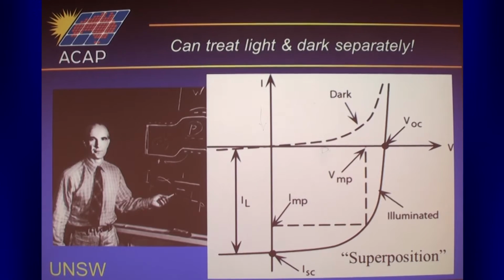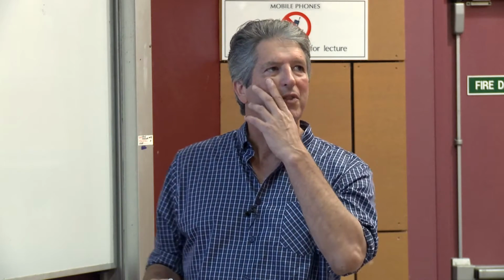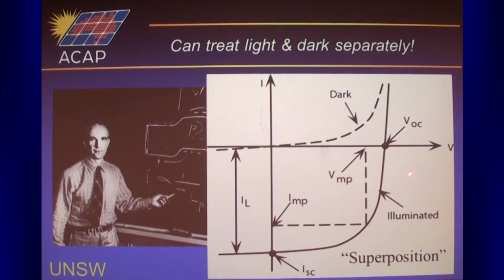So you want to suppress all the dark currents in a solar cell. So you want to push this curve out as far as you can. All this light generated current is determined by generally other design parameters of the cell. So you can sort of optimize the voltage, this open circuit voltage, and the current separately. At least that's what we thought, but I'll show it's a little bit more interrelated than that.